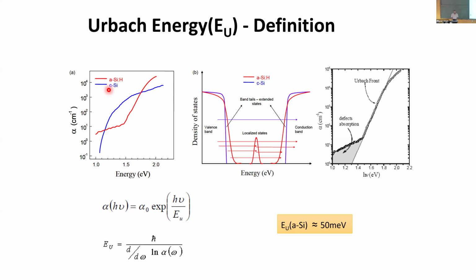If you look at the absorption equation, it's basically exponentially dependent, and in the denominator is the EU, the Urbach energy. So if you pull that out, it's nothing but the slope of this absorption curve you're seeing here. So if you plot it on a log linear plot and take an inverse of it, that's what gives you the Urbach energy.